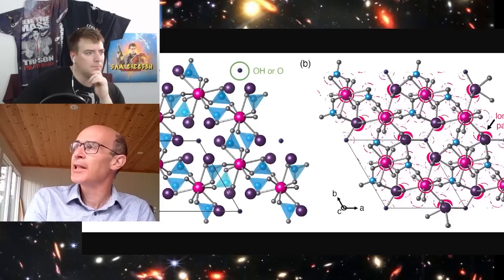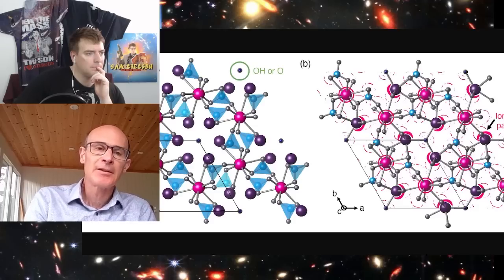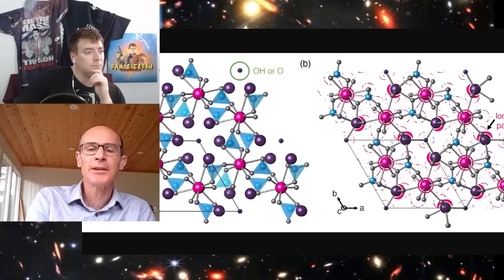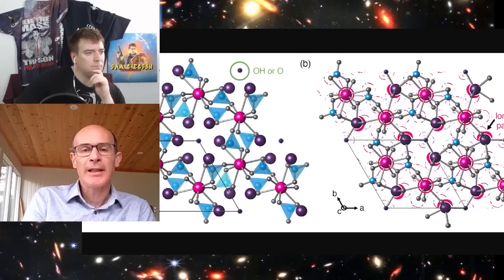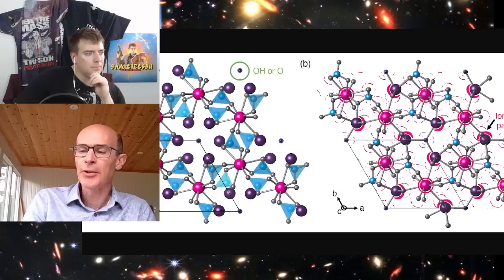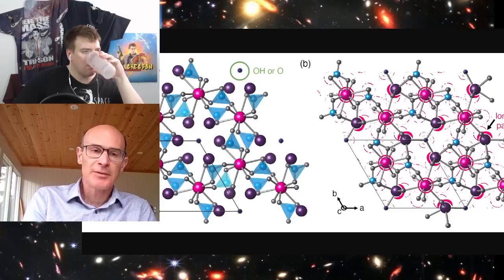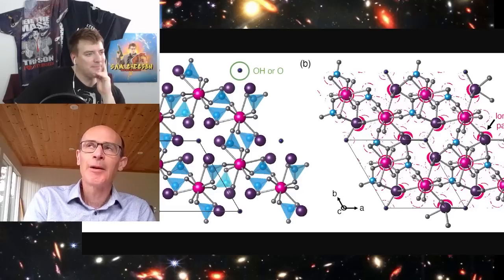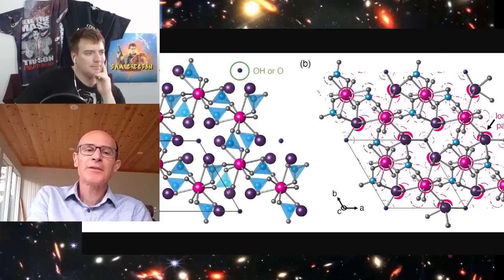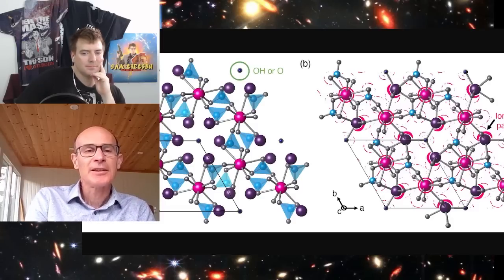If you were to take lead apatite and substitute some of the lead ions by copper ions at the 10% level, one would normally expect that compound to be an insulator, and you would expect it to be paramagnetic, because the copper ion, if it's a copper 2+ ion, would have one unpaired electron, and that would mean that the compound would be attracted weakly to a magnetic field. So it would behave as a paramagnet. So I would be surprised if that compound was exactly as described. If it was really that composition, I would be surprised if it was conducting, let alone superconducting.